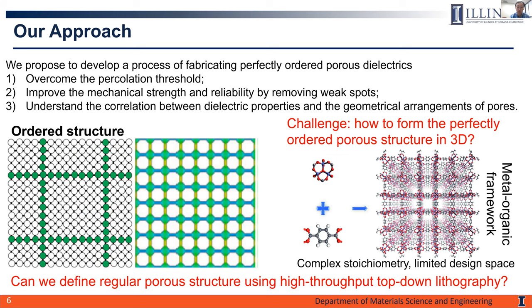One possible solution is to go from a random pore structure to a perfectly ordered pore structure. In this case, the porosity will not be limited by the percolation threshold since we're not dealing with a random system. Moreover, the mechanical and electrical stress will be uniformly applied to the whole structure. So the actual mechanical strength and electrical reliability will be dramatically improved since the weak spots causing catastrophic material failure will be largely eliminated.